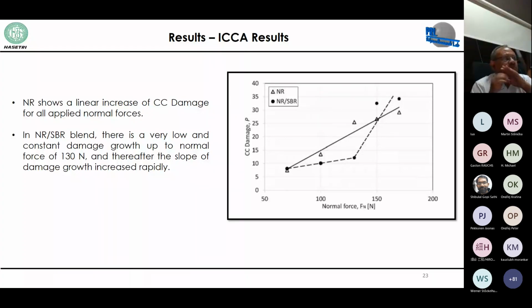So you can see that for NR SBR compound, the damage is low, maybe up to 130 Newton, the normal force. And after that, it is showing higher values, specifically at 150 Newton. So therefore, one should be very careful while selecting the compounds with respect to the application part. And this is also another challenge, how to quantify the tearing energy level or the severity level from a very smooth road to a very rough road. Which is practically impossible to do.